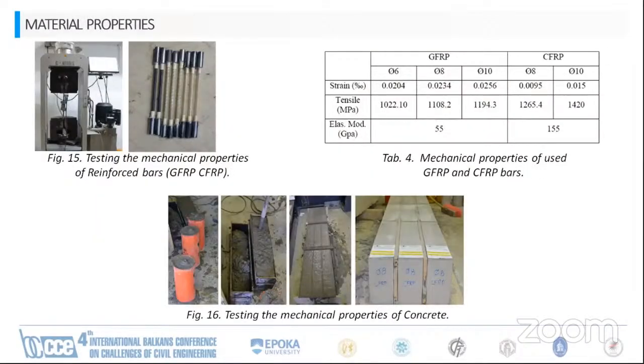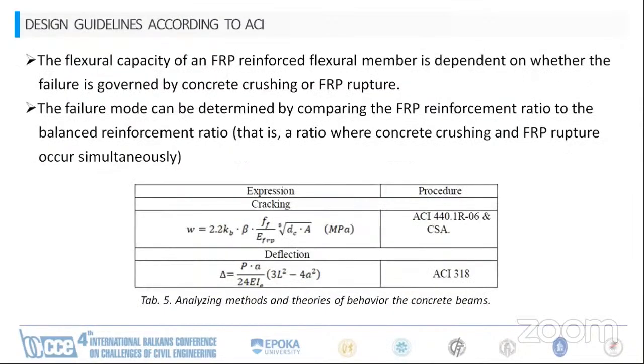The procedure of testing consists of first testing the mechanical properties of GFRP and CFRP, then testing the mechanical properties of concrete, and finally testing the reinforced beams with GFRP and CFRP overall. The flexural capacity of an FRP reinforced flexural member is dependent on whether the failure is governed by concrete crushing or FRP rupture. The failure mode can be determined by comparing the FRP reinforcement ratio to the balanced reinforcement ratio, that is, a ratio where concrete crushing and FRP rupture occur simultaneously.